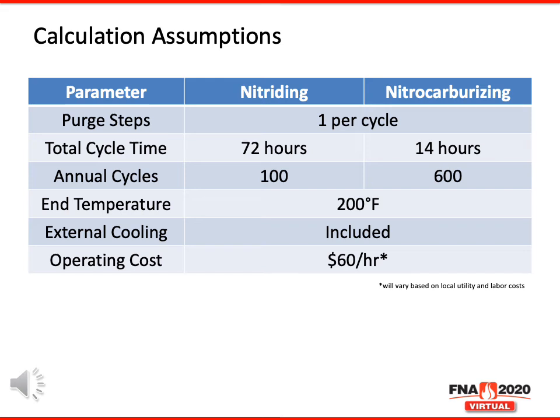So over the course of a year, depending on how many hours a plant or an operation runs, you may be able to get 100 cycles in at 72 hours each, or 600 cycles in of a 14-hour nitrocarburizing cycle. If we assume the cycles end at 200 Fahrenheit, the external cooling system, we assumed it would be included. As you could tell from the previous graphs, not having any type of cooling just isn't practical in any way. So we're going to assume that's already included as part of the system.